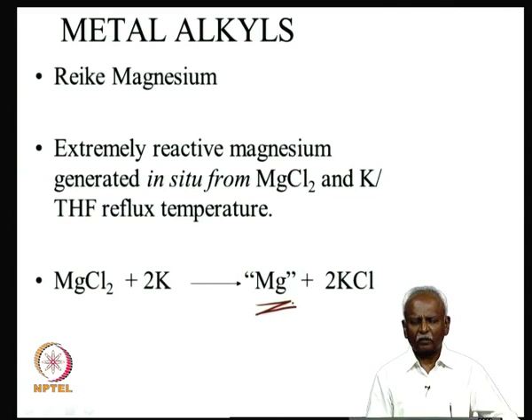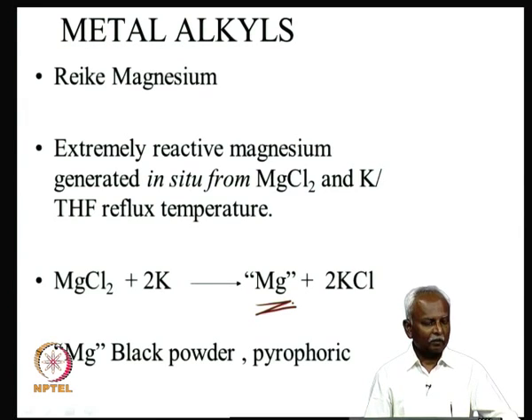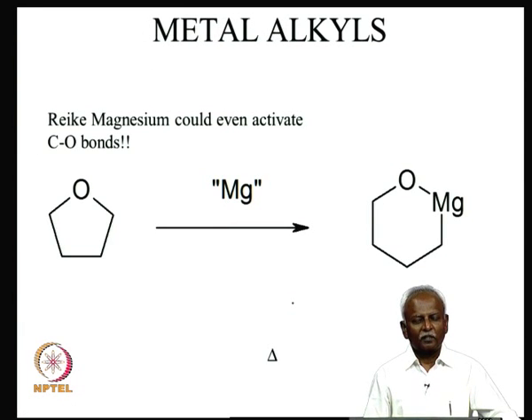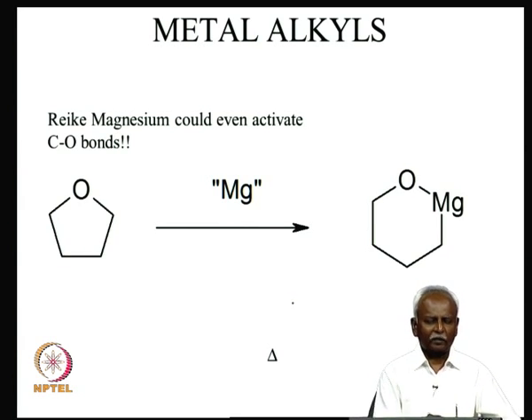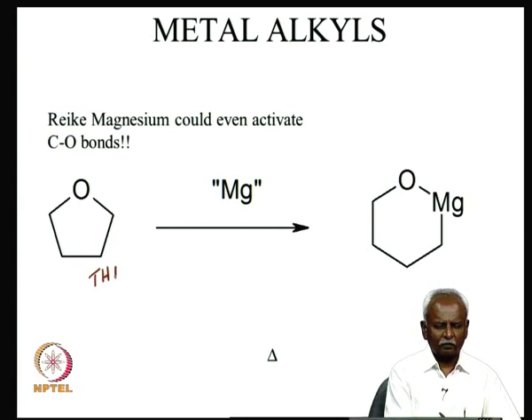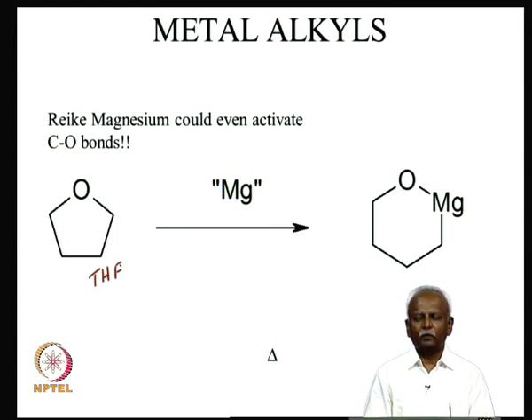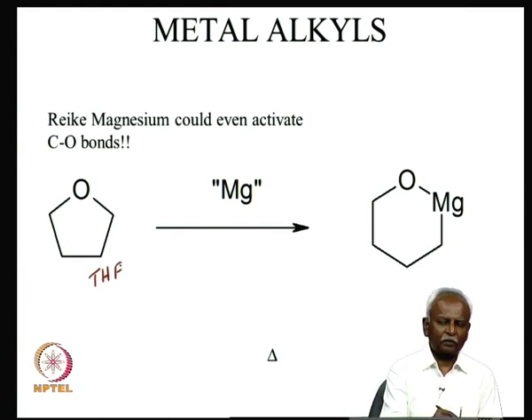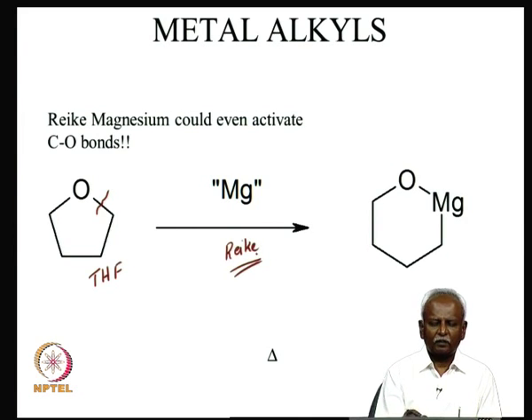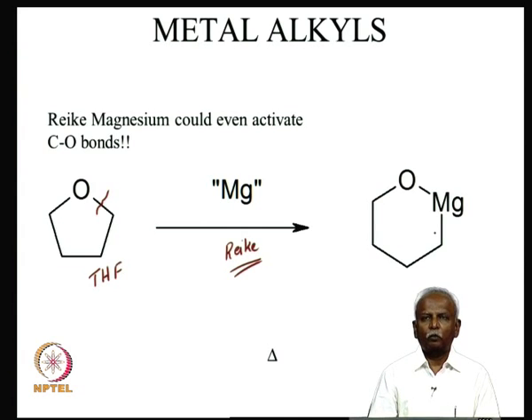So this is a pyrophoric powder that is formed by reduction of magnesium 2 plus using very reactive potassium. This is called Rieke magnesium, and it has some very interesting properties apart from the fact that it is not a shiny metal, but a black powder, and it can catch fire when you expose it to air. It's so reactive that THF, tetrahydrofuran, which is a common solvent used when you make Grignards, can be cleaved. So even the CO bond can be ruptured in the presence of Rieke magnesium. Rieke magnesium has a tendency to break the CO bond and form the 6-membered metallocycle.